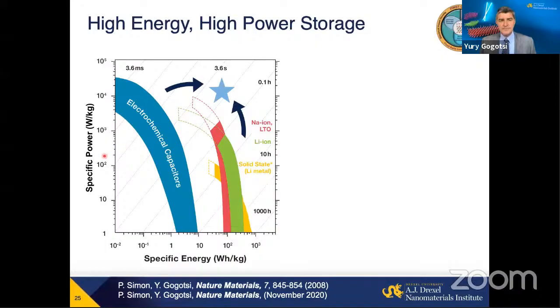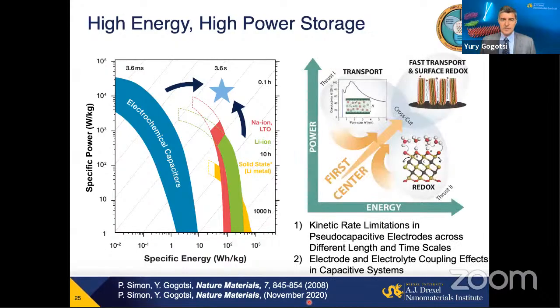But getting there is not easy, because this Ragone plot shows specific energy, which defines how far you can go, and specific power, which defines how fast you can charge, discharge, or accelerate, on a log-log scale. So getting to this point of, say, minutes charge and discharge is not easy. It's an order of magnitude increase in power. And getting from the energy density of a supercapacitor is even more challenging, because a couple of orders of magnitude in energy density are needed here. So how can we get there? What do we need from materials to get there?